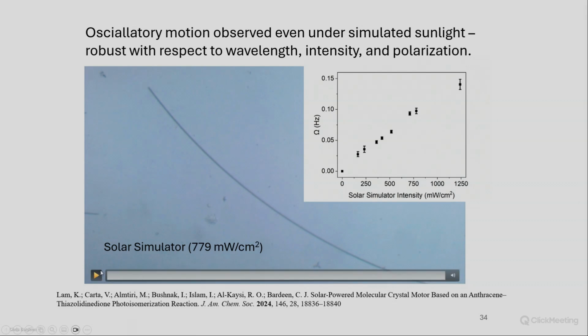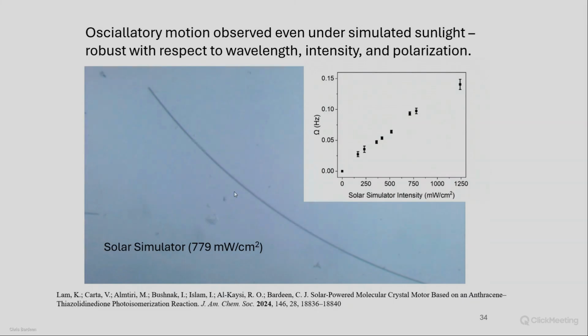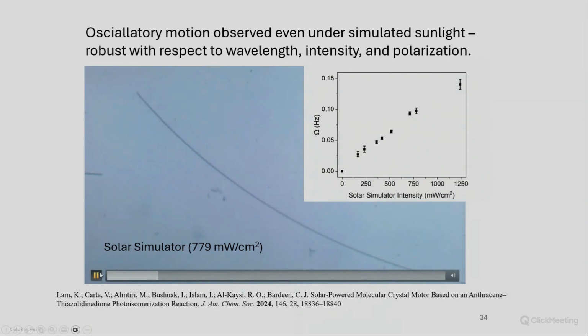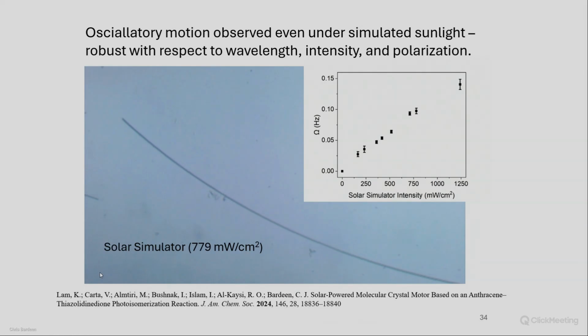And this is under broad wavelength light. So even at sort of ambient solar intensities, you do see motion under a microscope for a solar simulator. So this is relatively high, but at lower intensities that correspond to your sort of daytime illumination, you will still get motion. So this was also published last year, just to demonstrate that you could get this type of molecular crystal motor type motion.